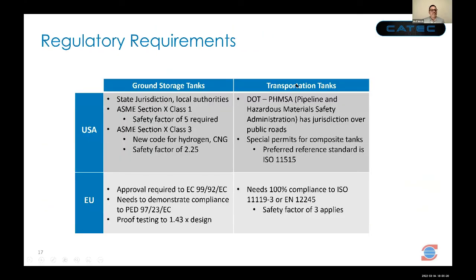The safety is number one, of course, and there are many regulations that we need to go through for ground storage as well as for transportation. For example, in the US, there are standards such as ASME Section 10 that if it is steel, safety margin of 5, but if it is class 3, which is the composite pressure vessels, is 2.25. So that gives a tremendous cost advantage. And the safety margin for composites is lower because the carbon has very unique fatigue characteristics. There is not too much drop in the fatigue strength. That means the safety margin can be lower.